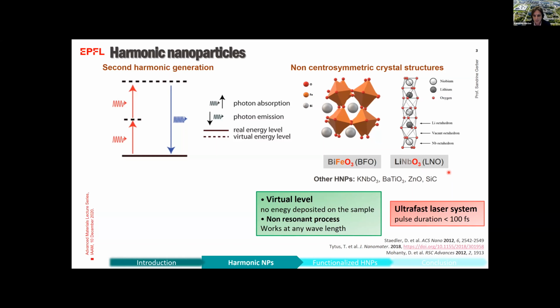And these nanoparticles are really characterized by their second harmonic scattering properties, meaning that when two photons coinciding in time and space are combined by the system, while in fact their frequencies are not adding up to an existing transition of the material, there is a possibility to generate an emitting photon at exactly twice the frequency and half the wavelength.